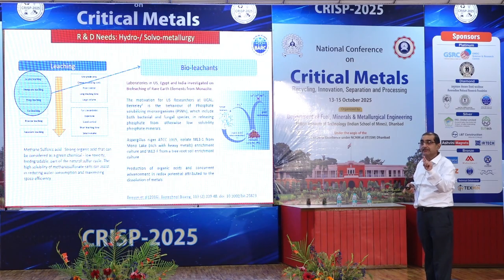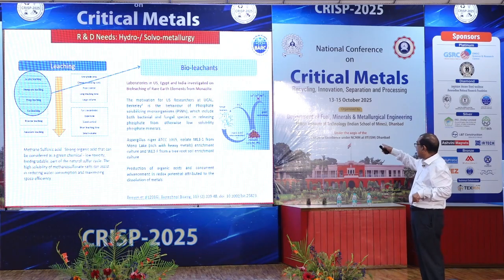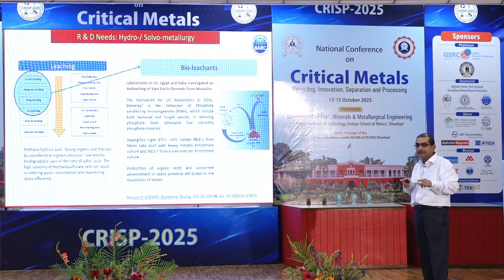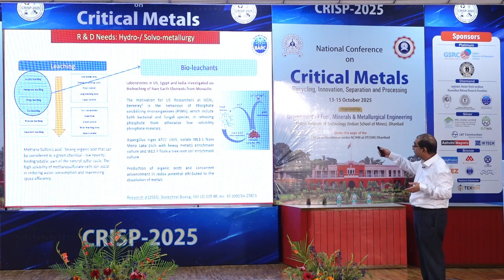Let us take from nature some good lesson. University of California has done that. What they have seen is how the plants are able to break the refractory apatite and consume phosphorus. From that they developed some variants which will be able to break monazite. See, monazite is very refractory. Its melting temperature is very high and the bond strengths are very high. That is why rare earths require either sulfation roasting or temperatures above 700-800 degrees centigrade for breaking those bonds. But they have observed nature.